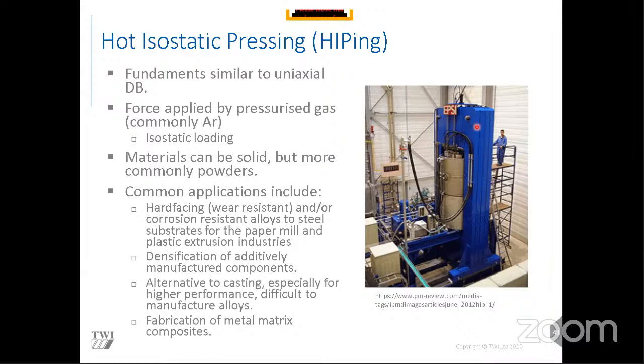You can use it to densify additively manufactured parts - so you can take components 3D printed using laser additive manufacture, put them into your hip, and it will remove all porosity from your parts. But you can also use hipping as an alternative to casting. You can design and develop cans with an intricate internal shape, fill with powder, hip, and you've basically got a cast part with no porosity.